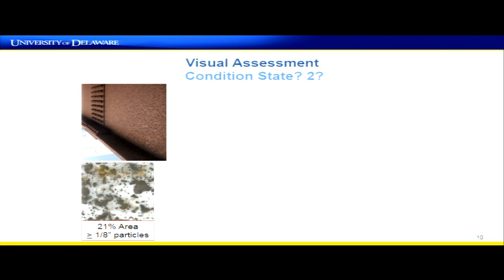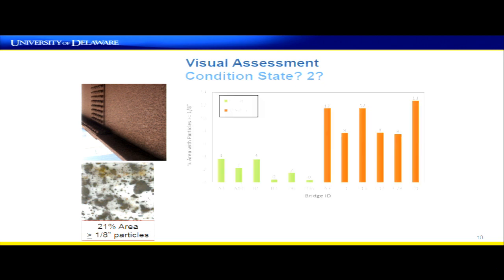The benefit of that is we see a clear gradient in what these tape samples look like for bridges that have pitting and bridges that had no defects. So the ones in green are the average percent of these large particles for bridges that were in condition state 1. And then the ones in orange are the same data for bridges that were in condition state 2 with pitting. So this allows us, for these intermediate cases where it's not pitting, but it's also not exactly no defect either, to have some quantitative measure for classifying the performance.